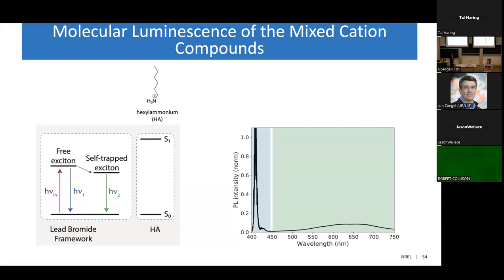So for the pure hexyl ammonium lead bromide perovskite, all of the emission that we see is coming from the lead bromide framework. All right, so we see emission from the free exciton, which is the part shaded in blue, as well as what's called a self-trapped exciton. So these are really soft lattices. So the exciton can actually get trapped by its own potential, and it produces this really broad red-shifted emission, which is the part shaded in green. But there's no emission coming from the organic part because we don't expect any interaction at this interface.